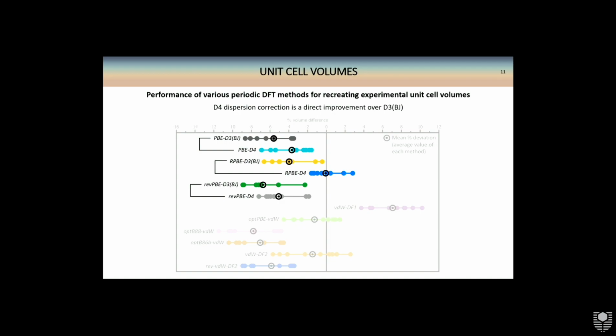To begin with, these first six are three different functionals, which are the PBE, the RPBE, and the revPBE, and I paired them with the slightly older D3BJ correction and then the D4 dispersion correction. And in every case, the D4 dispersion correction has been a direct improvement over the D3BJ, which you'd hope it would be, being a more recent version. Every time it has brought the percentage volume difference at least 2% closer to zero, and usually we saw it also slightly reduce the range over which the results were spread.